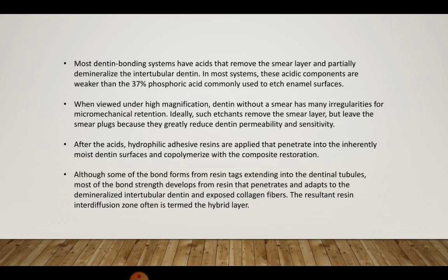Meaning that when we use these mild acids inside the dentine bonding agent, they etch and remove the smear layer that is on the dentine, but they leave the smear plugs which are inside the dentinal tubules, because if they remove these smear plugs, it can cause increased dentine permeability, and thereby increased sensitivity.